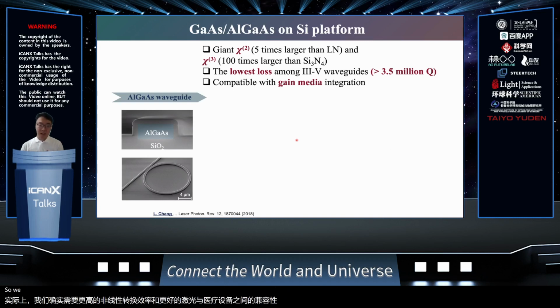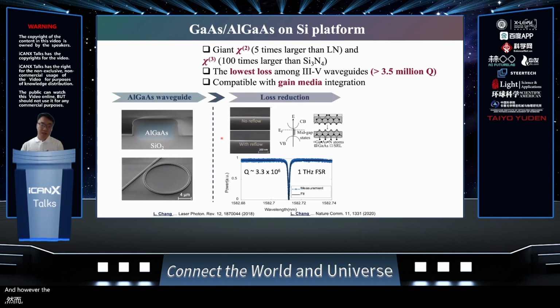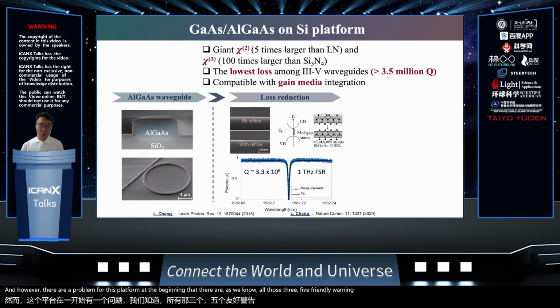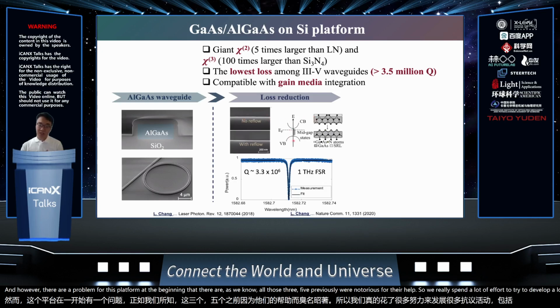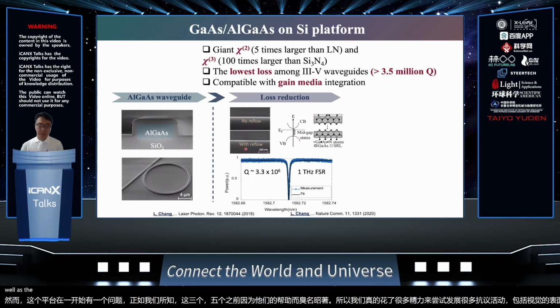So we started to develop another material platform, which is GaAs/AlGaAs on silicon. This platform is made by heterogeneously integrating high quality AlGaAs or GaAs film onto an oxide silicon substrate. However, the problem for this platform at the beginning is that, as we know, all those III-V materials were previously notorious for their high loss. So we spent a lot of effort to develop a low loss process, including surface passivation as well as optimized lithography.